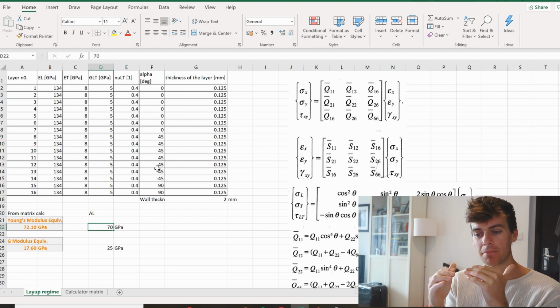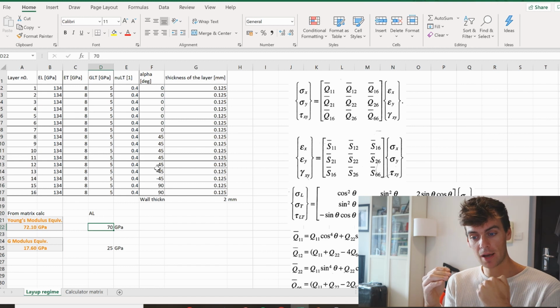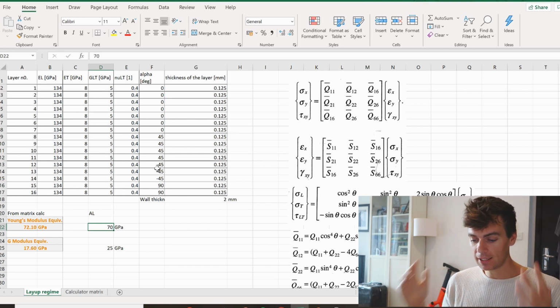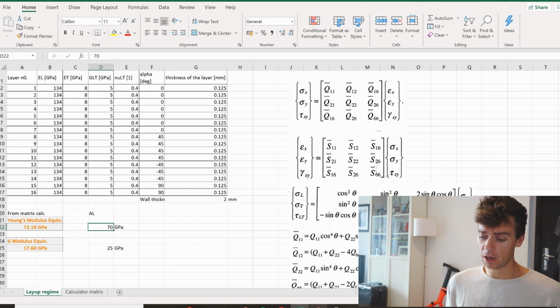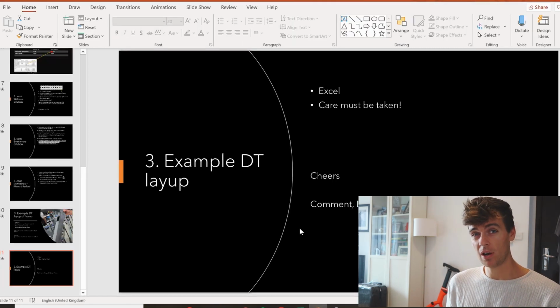That's why we don't see these massive differences in weight between aluminium and carbon, because with the carbon one, the layup becomes so complex, you just need to add more to bring the stiffness up. And anyway, that's my whole point about carbon fibre. It's not this wonder material, it's very hard to get right, and I wonder if anyone has actually come up with the optimized layout for a down tube or the whole bike, because it is so difficult.